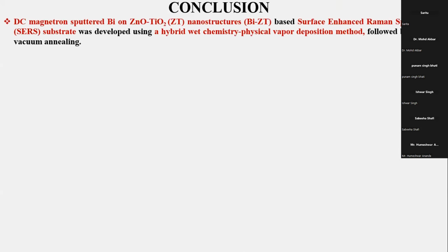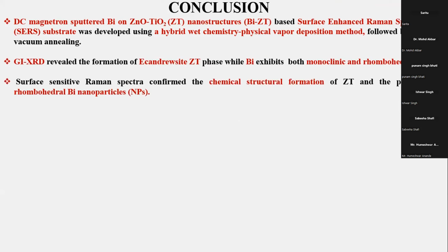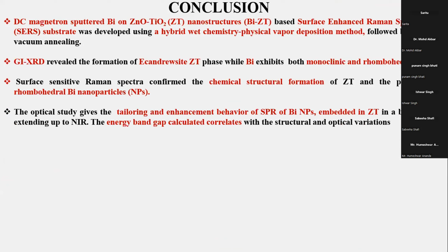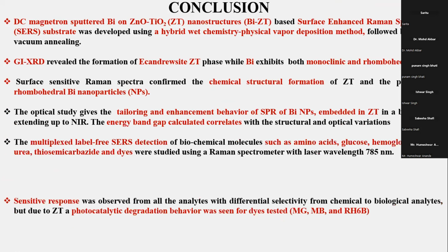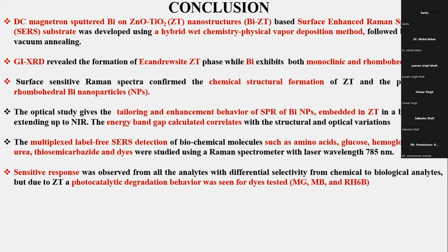So as a conclusion, this magnetron sputtered bismuth on top of ZnO-TiO2 (ZT) nanostructures-based SERS substrate will be a potential candidate for multiplex detection, and GI-XRD revealed the Ecandrewsite, which is a novel structure with monoclinic and rhombohedral phases. And the optical study confirms the energy band gap correlation and the tailoring behavior of the SPR.